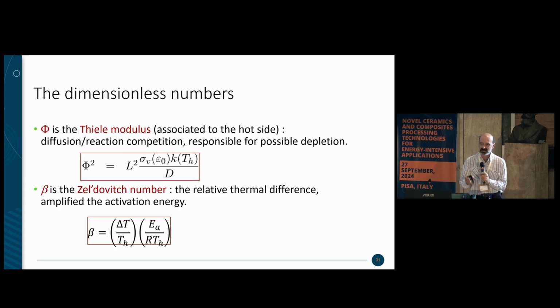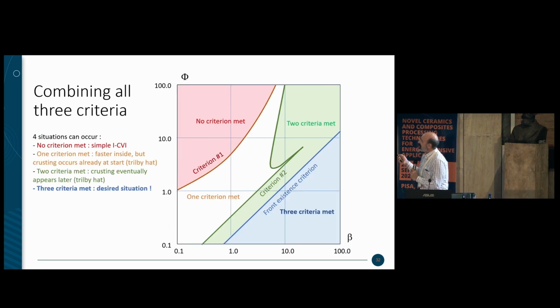And one has to look at the fact that the activation energy is something that amplifies the importance of a thermal gradient, okay? And, well, in that space, we have shown that 4 types of situations can occur. Well, the classical ICVI or isothermal CVI situation is there, in which you simply have a premature crusting of your preform. When one criterion is met, it means that the reaction rate is faster inside, but crusting ends up occurring.